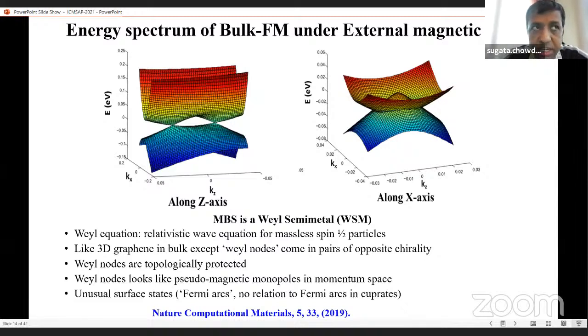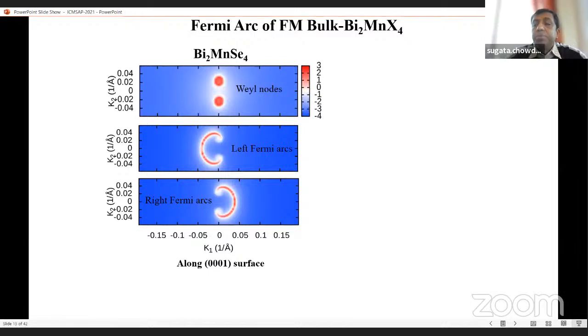And that tells us that the ferromagnetic phase of this MBS is really a very good candidate for different kinds of applications. What we found is that Weyl nodes come in pairs of opposite chirality, the Weyl nodes are protected, and a Weyl node looks like a pseudo-magnetic monopole in momentum space. There is an unusual surface state, the Fermi arc. So what is happening in the Fermi arc? They are connected to each other.